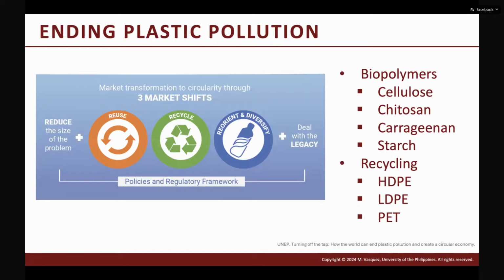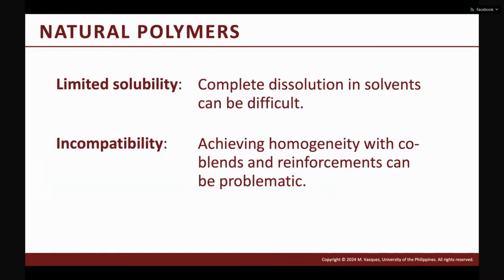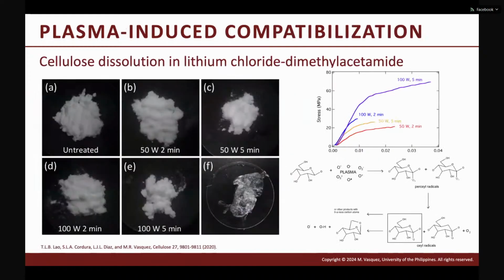Now, another motivation for us on why we want to use plasma-based modification is for polymeric materials, especially biopolymers. For natural polymers, processability is a very big issue. Not all natural polymers can be dissolved in solvents, and it's very difficult to dissolve them. So what we want to do is improve their dissolution by treating with plasma. Here's an example. This is cellulose, and we were able to improve the dissolution of cellulose when we pre-treat the cellulose with plasma. Cellulose is a candidate material for food packaging.